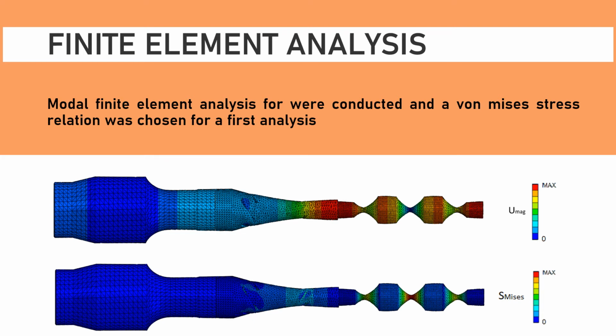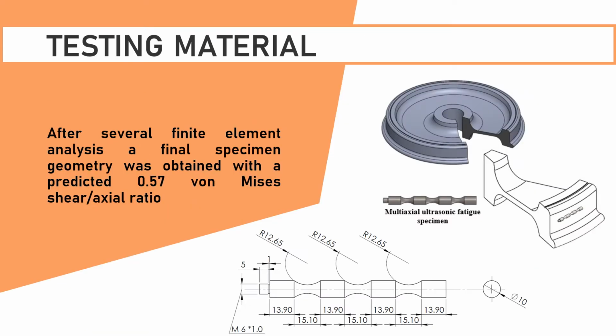After determining some material properties of the rim section of the wheel, many finite element analyses were performed using the whole set, horn, booster, and specimen, for several different combinations of dimensions of the specimen, until a final geometry was obtained with the stress relation of von Mises. This stress relation was chosen in order to compare to already made conventional fatigue tests with a tension torsion relation of von Mises. So after many finite element analyses, a final geometry was obtained, presented in this slide. This geometry has the predicted 0.57 von Mises shear axial ratio.